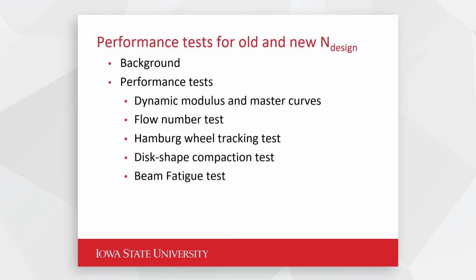So we go to the next slide and we look at the different performance tests. It's pretty extensive in terms of dynamic modulus, getting master curves, flow number tests for rutting, Hamburg wheel track testing for rutting and moisture damage, disc shape compaction tests for low temperature cracking, and then beam fatigue tests for fatigue cracking as well. And then finally, we were looking at doing some analysis on the results.